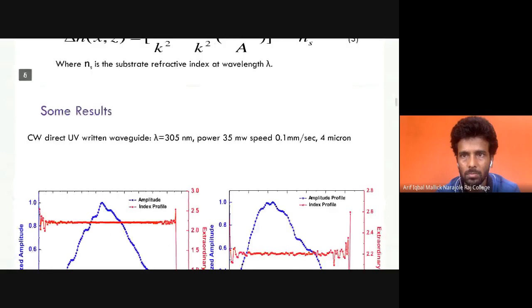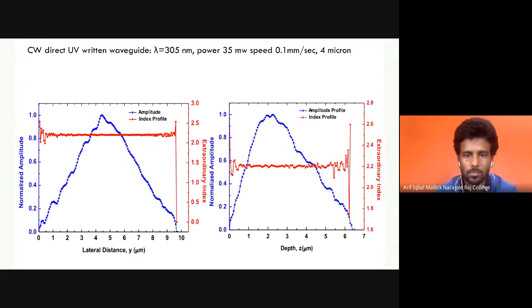Some results: continuous wave direct UV written waveguide at 305 nanometer writing wavelength, 35 milliwatt power, 0.1 millimeter per second scanning speed. The blue curve indicates the raw data of the amplitude profile. If we take this raw data and extract the refractive index profile, we get the red curve of the refractive index profile, which is an unexpected result. And to get the actual refractive index profile, we have to eliminate the noise present in the amplitude profile. We have to eliminate this noise by a third order low pass Butterworth filter.